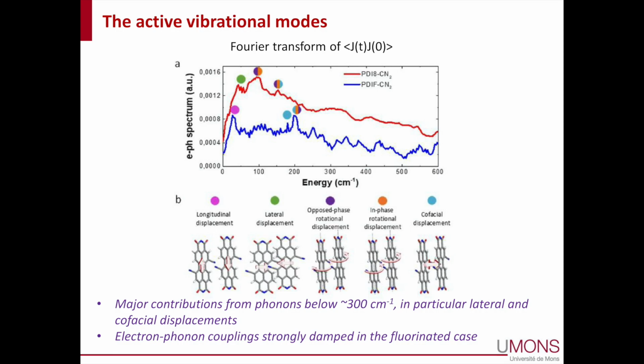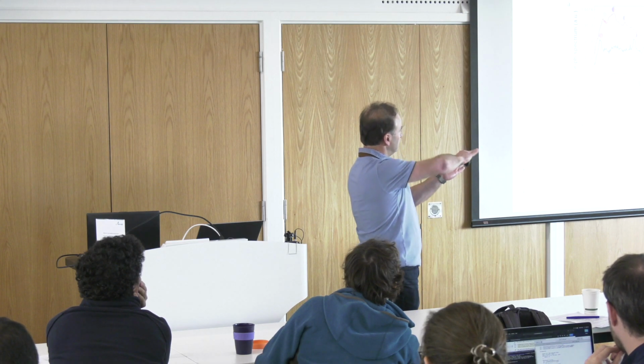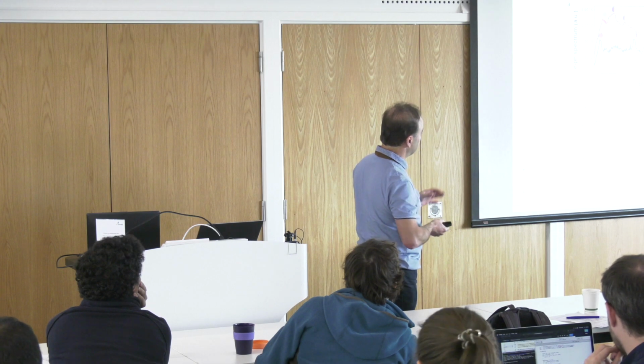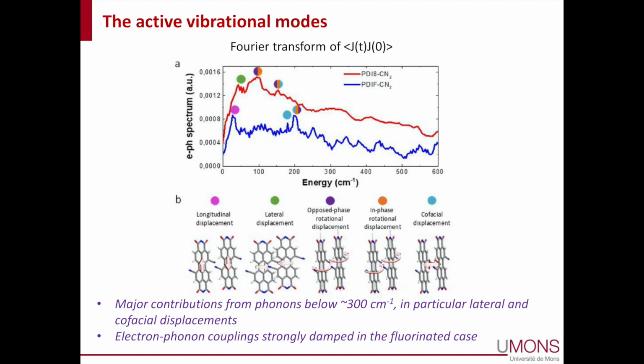And we see that they involve both longitudinal displacement of the molecule, lateral displacement of the molecule, rotational motion of the molecule. So all these modes seem to contribute, in those molecules, to give rise to large electron-phonon coupling, and therefore they act in concert to collapse the wave function and reduce the charge carrier mobility.